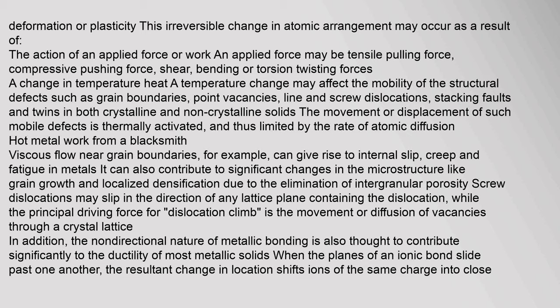A change in temperature may affect the mobility of structural defects such as grain boundaries, point vacancies, line and screw dislocations, stacking faults, and twins in both crystalline and non-crystalline solids. The movement of such mobile defects is thermally activated, and thus limited by the rate of atomic diffusion. Viscous flow near grain boundaries can give rise to internal slip, creep, and fatigue. In metals, this can also contribute to significant changes in microstructure like grain growth and localized densification due to elimination of intergranular porosity.